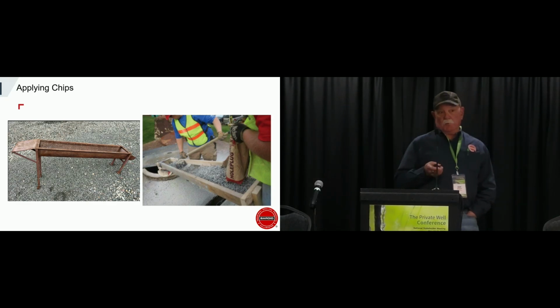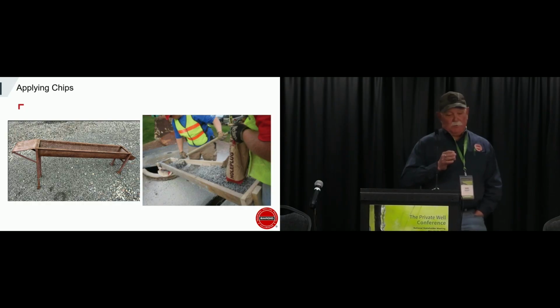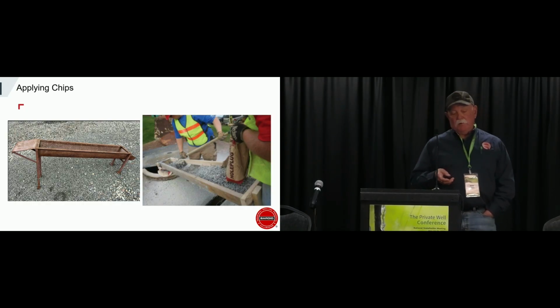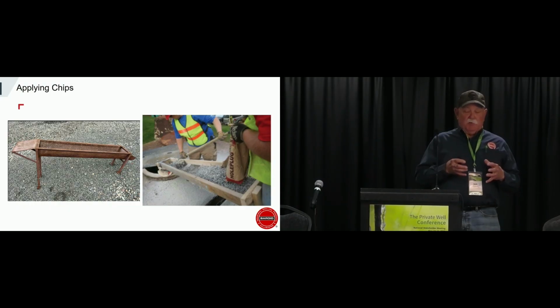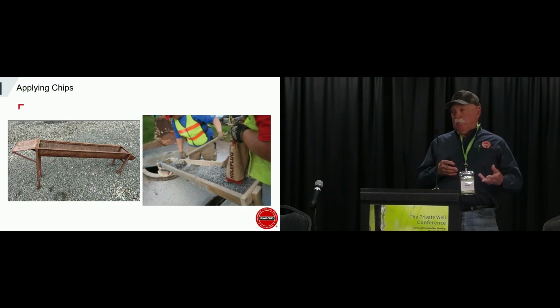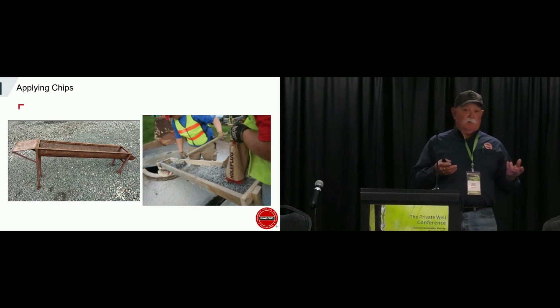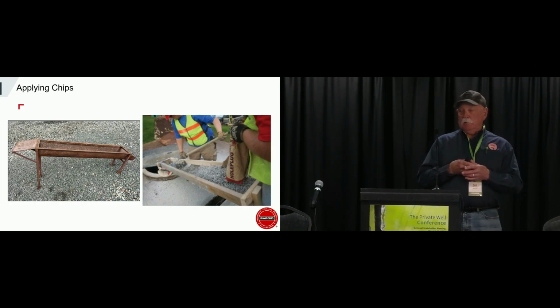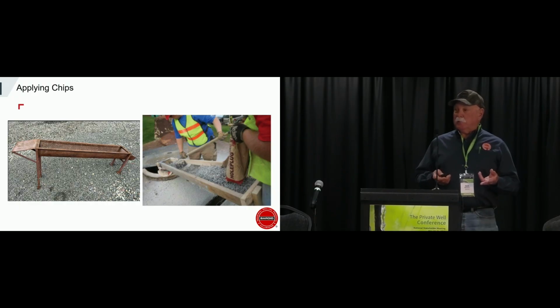And there's another thing: you should know the approximate amount of volume you have in the hole. We know that 1 sack of granular bentonite, the 3/8 size, is roughly 0.7 cubic feet. So if you know your approximate amount of material that you need and you use half of it, I'd say you've got a problem somewhere. So it's likely a bridge.